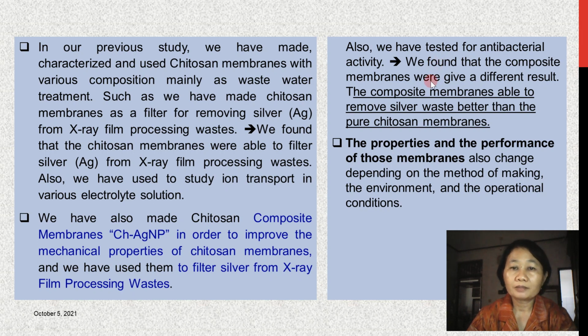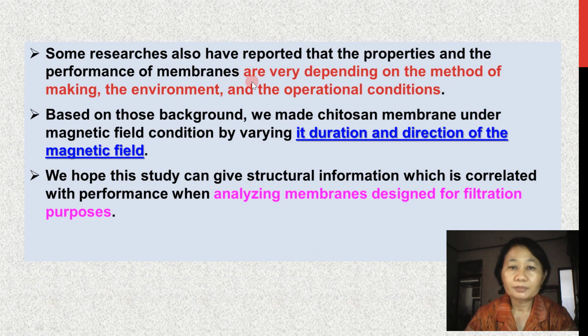We found that the composite membrane gives a different result. The composite membrane is able to remove silver waste better than the pure chitosan membrane. Also, the composite membrane has more antibacterial activity compared to the pure chitosan membrane. The properties and the performance of those membranes also change depending on the method of making, the environment, and the operational condition. Some researchers have also reported that the properties and performance of membranes depend very much on the method of making, the environment, and the operational condition.